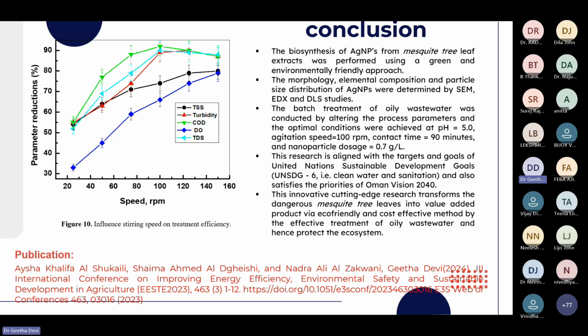And in conclusion, silver nanoparticles were successfully biosynthesized from mesquite tree, and this was applied in oily wastewater treatment, and the optimum conditions were obtained at pH of 5, agitation speed of 100, contact time of 90 minutes, and nanoparticle dosage of 0.7 gram per liter. This wastewater treatment is also in line with the United Nations Sustainable Development Goals.